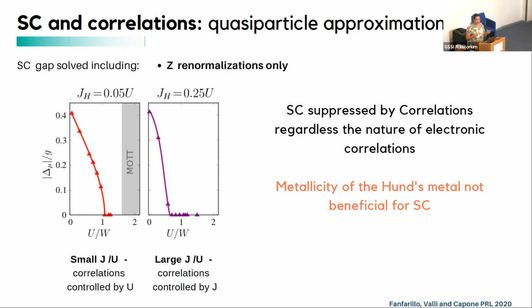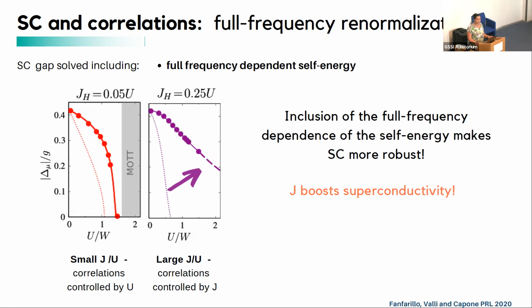But what happens if I now take the full frequency dependence of the self-energy and solve the gap in this way? You see that there are mainly 2 effects. In both cases, the inclusion of the full frequency dependence of the self-energy makes superconductivity more robust with respect to the approximation calculated using only the Z factor. And the second aspect is that at large J, you see clearly that J is boosting superconductivity to survive to very high values of U.